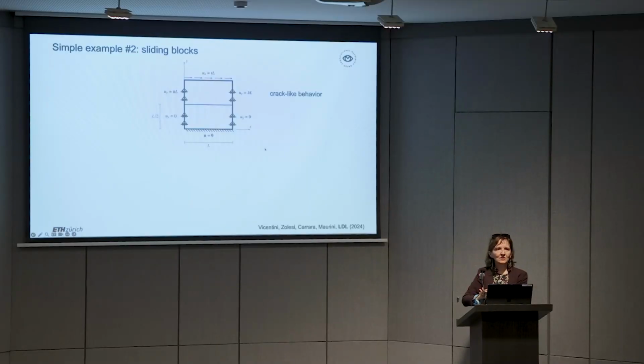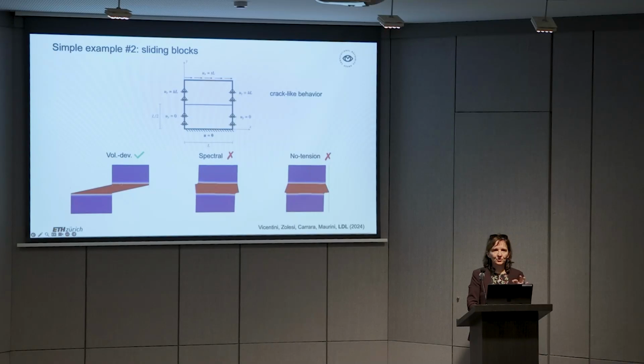So imagine you have one block, and you have an initial crack between the upper side and the lower side. So you put it there from the very beginning. You also want to now displace the upper part with respect to the lower part, and you expect a rigid body motion, right? Because there's a crack in between. So this is not about nucleation now. Now this is about crack-like behavior. So the fact that across a crack you really want no shear stresses, because a crack in this setting doesn't have any friction between the lips. Now, the volumetric deviatoric is perfect, it will give you really rigid body motion, but both the spectral and the no-tension split will give you spurious shear stresses across the crack lips. And so that means none of the decompositions is really able to satisfy the requirements of nucleation under multi-axial stress states and crack-like behavior. The reason for this I'll try to explain in the next slides.